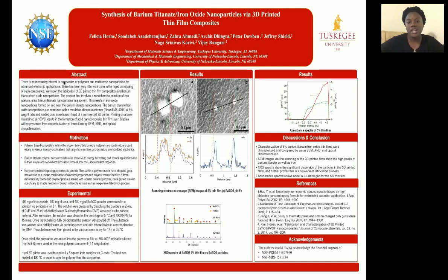If you see up top, we have image A and B. We were looking for the barium titanate alone through line scanning through the EDX SEM, and we were able to identify peaks for barium titanate. And then for image B, the same with the iron on that polymer matrix of the silicone. So that's just what that is. So we were able to identify that as well within that sample.